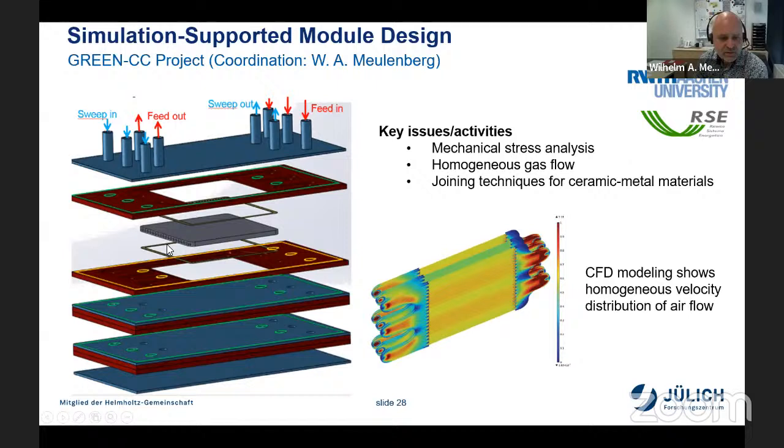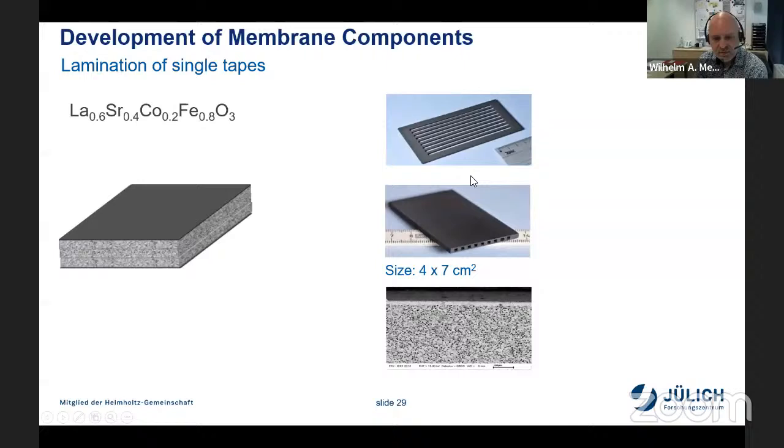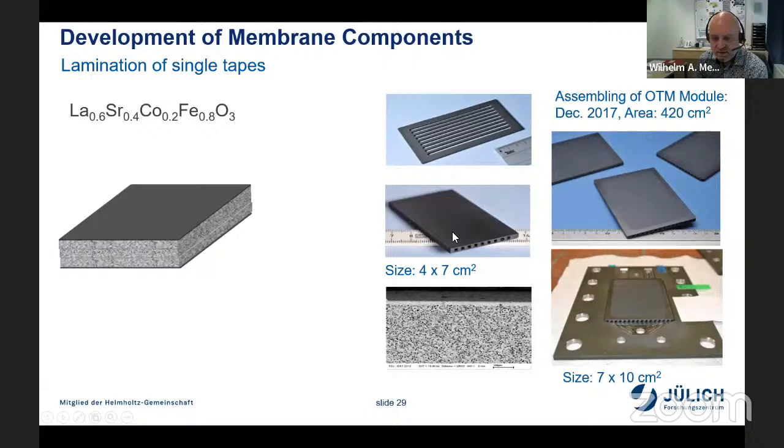But here, this membrane was very nice because it was built for an absolute pressure difference of up to five bars. And we manufacture it by tape casting and laminating. That means in a laminating step, we formed such a layer, and then we cut it on both sides, the membrane. And then we see we have here gas channels that are completely porous in the middle, and the surface has a gas tight layer. So, and yeah, now two slides on materials.